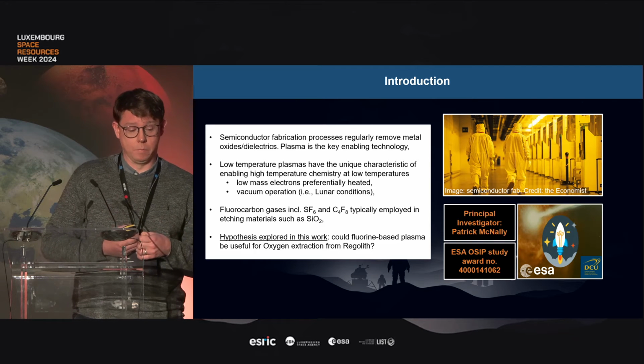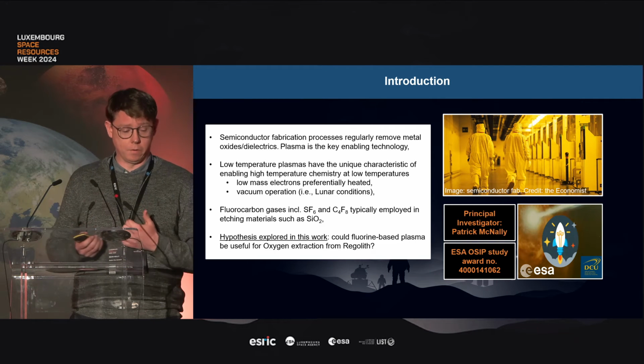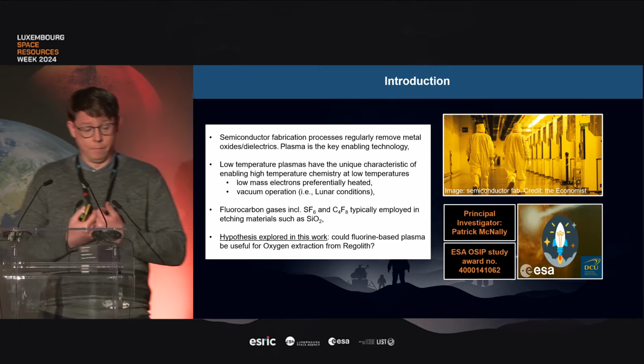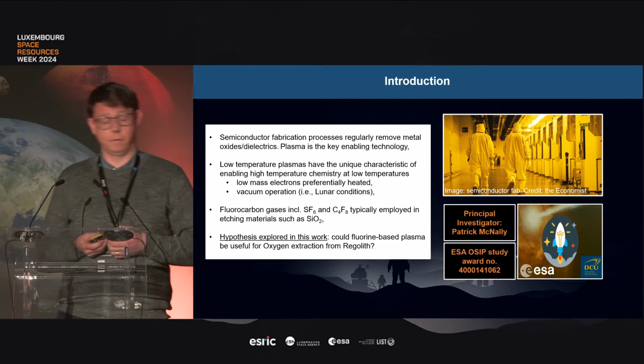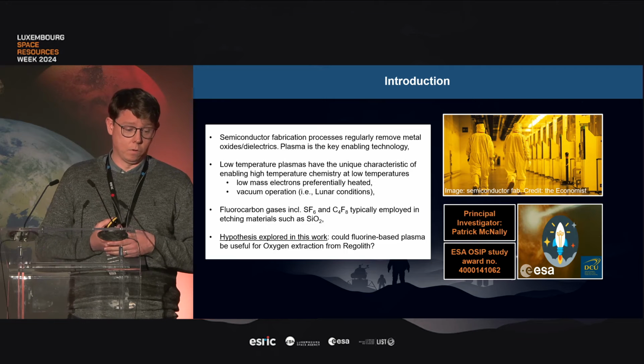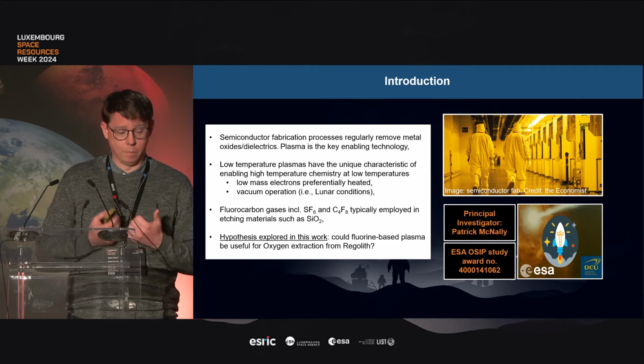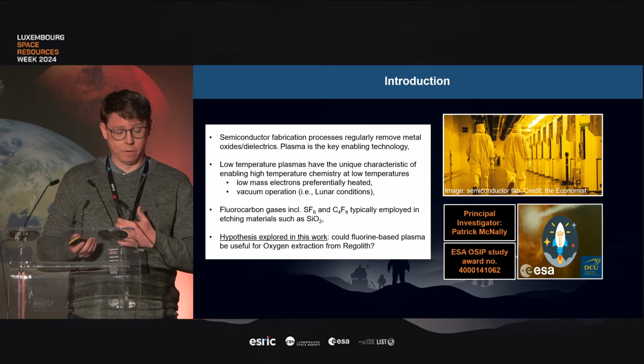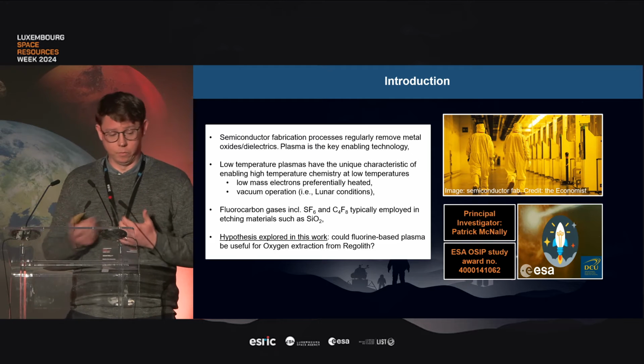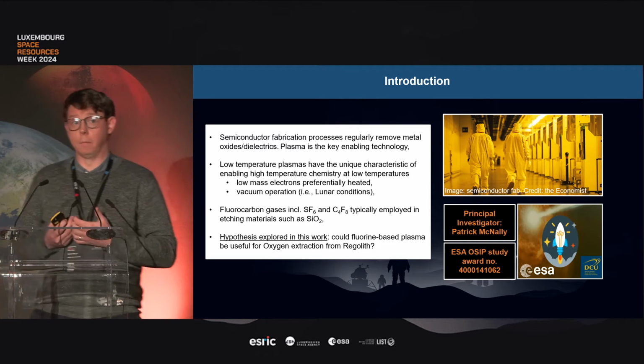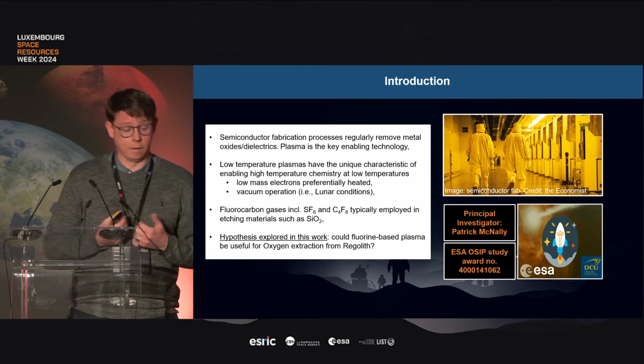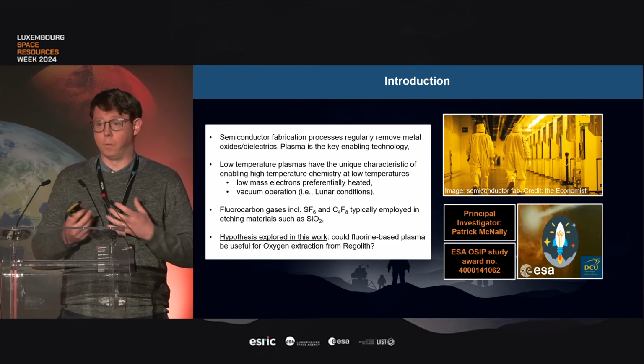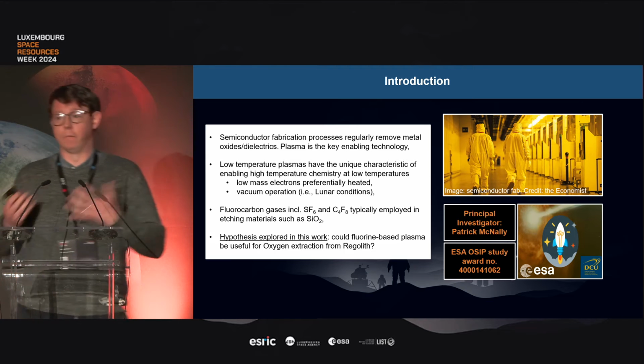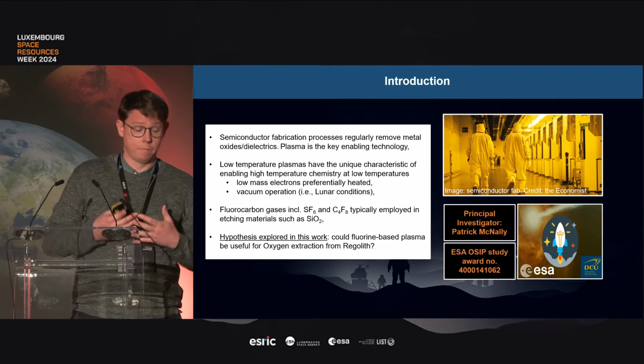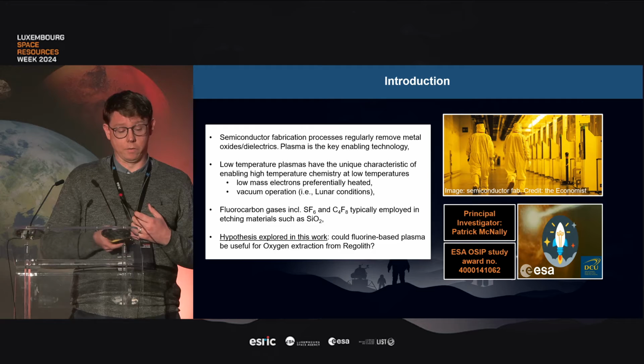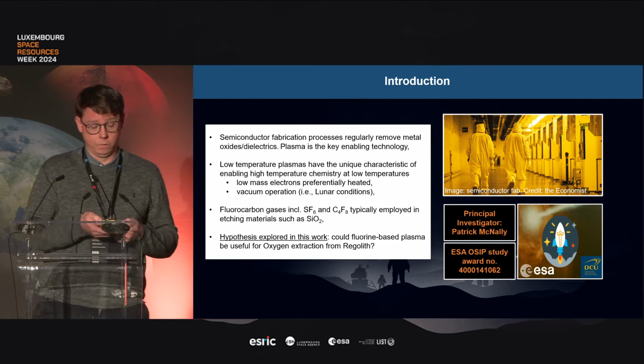And this has to do with electrons. They can be preferentially heated. They have low mass compared to the other species in the discharge. Also, they favor vacuum operation, so they're conducive to lunar conditions. So typically halogen chemistries and fluorocarbon gases are used, some containing sulfur, some like C4F8, which we'll discuss in a moment. And these are typically employed to etch chemistries like silicon dioxide. So the hypothesis, and this is a very exploratory work, is could a fluorine-based plasma be useful for oxygen extraction from regolith? So just to acknowledge the funding here is from an OSIP study to DCU.